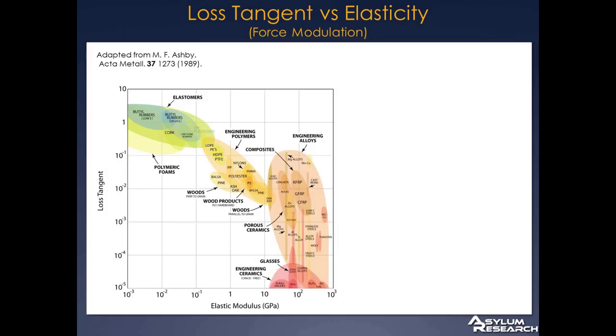And then the loss tangent is along the vertical axis up here. That ranges from 10 to the minus 5 to 10. As we go up in the loss tangent, these materials down here that are relatively stiff and have low loss tangents, things like glasses and certain kinds of ceramics, you know these materials and you know that they have low loss tangents because if you happen to hit them with a hammer, not break them but give them a little impact, they'll ring like a bell. They'll make a very nice single tone. You'll be able to identify that tone and it will go on for a long time because they're not lossy.